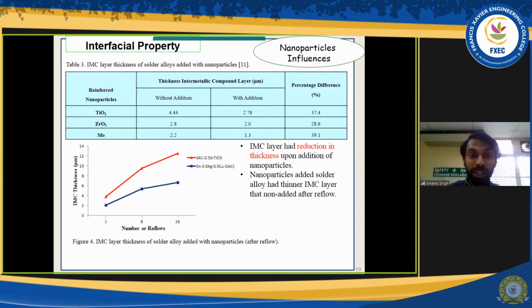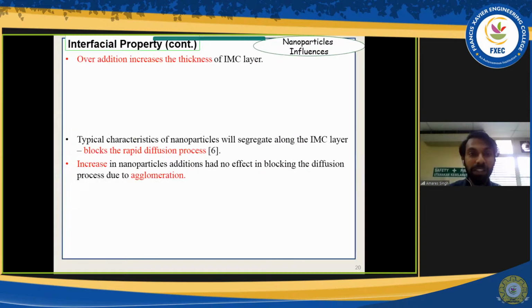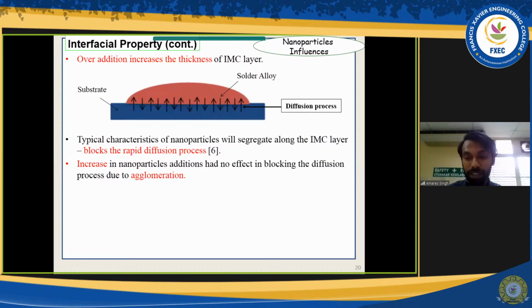So what happens when nanoparticles are added to these lead-free solder alloys? Without and with addition, upon gathering certain literatures, we could see the intermetallic compound layer thickness reduces quite drastically. Okay, I'll tell why, and therefore it preserves a thinner IMC layer. So let me just tell you what happens when the nanoparticles are actually at the interfacial layer.